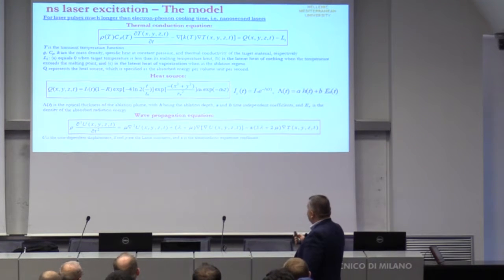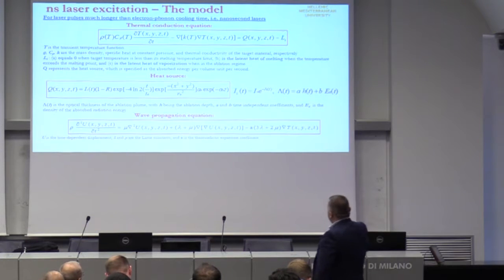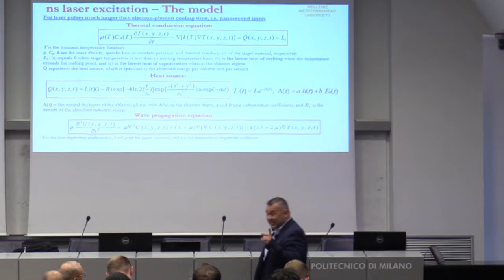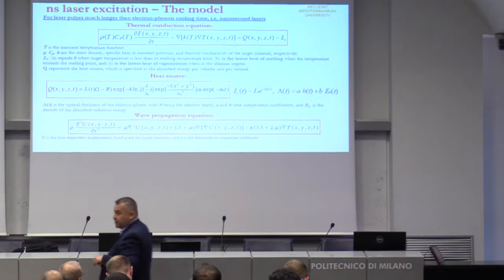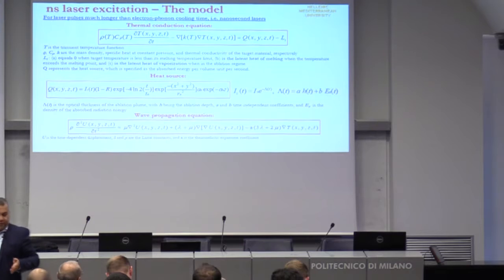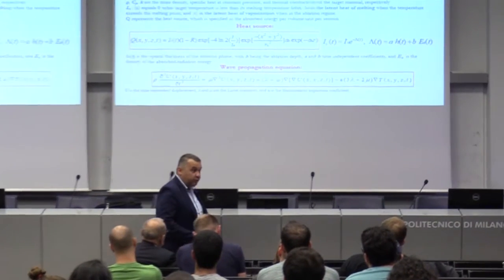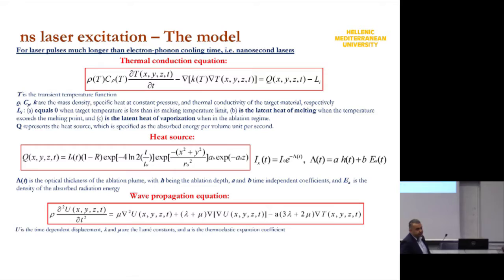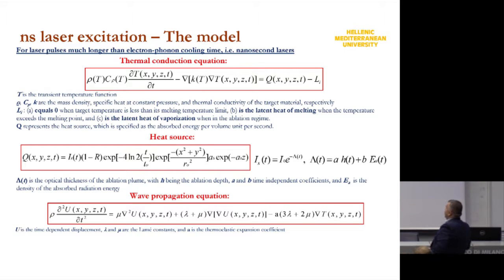So here we have a simple kind of thermal conduction equation, where the change of temperature of the material is the diffusion plus the laser source. And here is something, for example, the so-called latent heat. Because when we illuminate with a nanosecond pulse, very easily we can go from solid to melt material, to gas, or to plasma. So we have to take into account all these kinds of phase changes in order to study this.